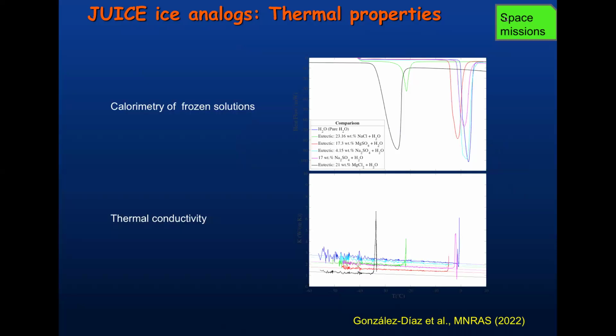So we measured the desorption of the molecules as you warm up the ice. And the thermal conductivity also behaves kind of linearly with temperature. And we also observe these spikes, which are an artifact of the way we measure thermal conductivity. But the interesting thing is that this artifact is due to heat that is being liberated by the ice during a structural change. So if the ice crystallizes, heat is released within the ice, and you see this spike in the thermal conductivity. So it's a very sensitive way to spot structural changes in these ices with salts.